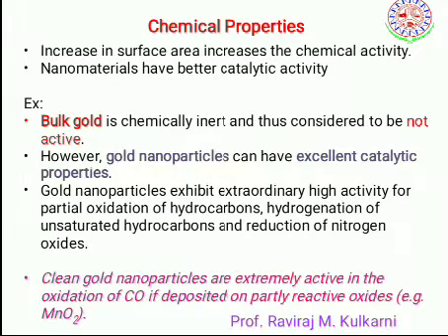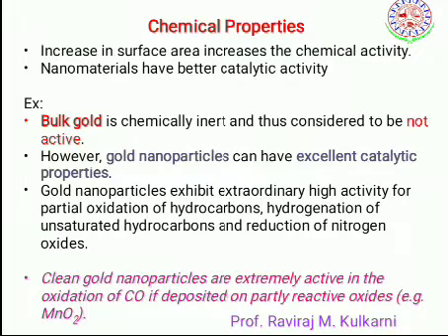Chemical properties also change. Increased surface area increases chemical activity, so nanomaterials have better catalytic activity compared to their bulk counterparts. Bulk gold is chemically inert. However, gold nanoparticles of 3 nanometer size have excellent catalytic properties and are used in the oxidation of carbon monoxide to carbon dioxide. Gold nanoparticles also exhibit extraordinary high activity for partial oxidation of hydrocarbons, hydrogenation of unsaturated hydrocarbons, and reduction of nitrogen oxides.